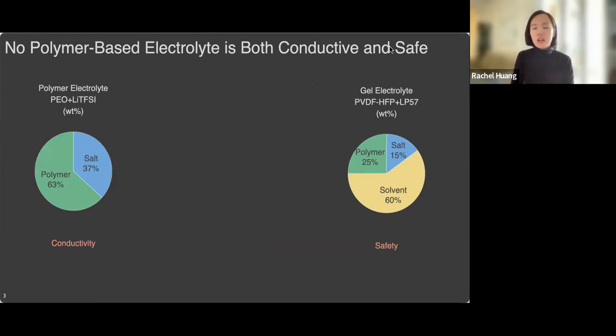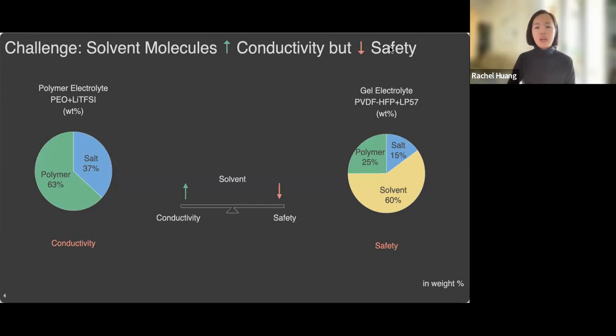To solve the conductivity issues of polymer electrolytes, we use gel electrolytes. We added more solvent molecules into those electrolytes. With the conductivity issue solved, gel electrolyte is still flammable, which brings back the safety issue with the existing solvent molecules. The conundrum is really on the solvent molecules. On one side, we need the solvent molecules to improve the conductivity. On the other side, we don't want the solvent molecules because they cause safety issues.